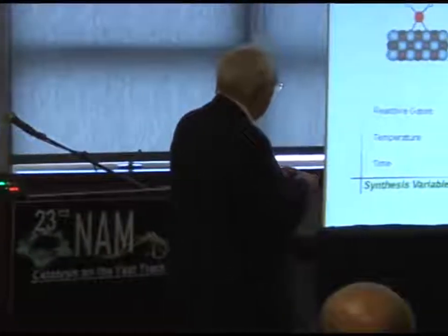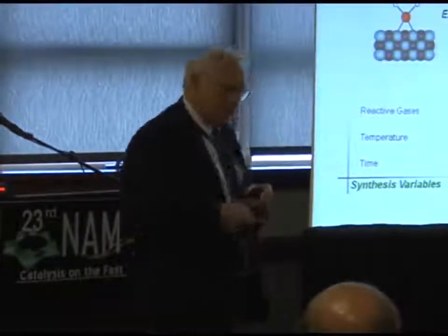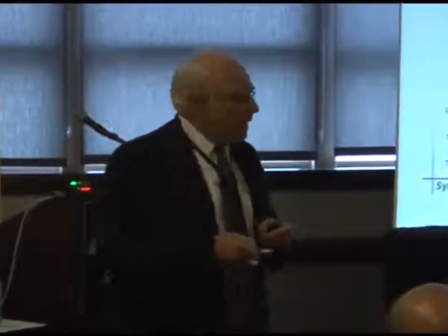So let's go back. This is the rhodium diethylene. The support we're going to talk about is just the MgO. I don't have time for the zeolite in this case. And so we can modify by ligand exchange, as we talked about. We can form dimers, and I didn't tell you quite how to do this, but simply treating this in hydrogen at 80 degrees gives us very high yield.